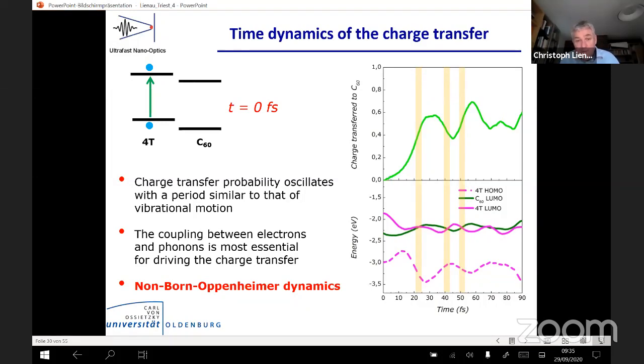But now, the motion of the nuclei brings the two systems into resonance. And at this moment in time, once the electronic states are aligned, the charge can flow. The nuclei keep on moving, they lift the degeneracy between the states again, so this stops charge transfer, or brings them back in a periodic fashion in resonance, and this is causing the coherent oscillations of the charge.